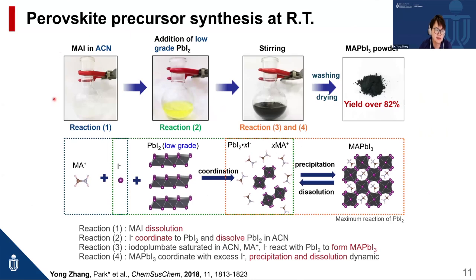At that time, I proposed a room temperature synthesis method using acetonitrile as the solvent. In this method, we dissolve methylammonium iodide first and add some low-grade 99% lead iodide while stirring, and we can see a black precipitate occurs. If we filter and wash it, we can get the MAPbI3 perovskite powder.